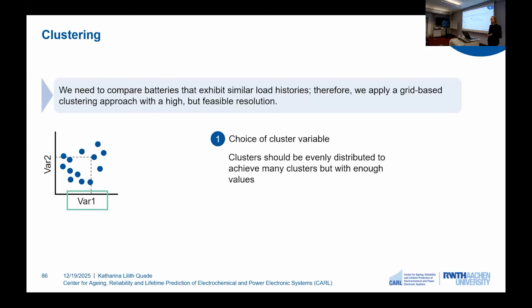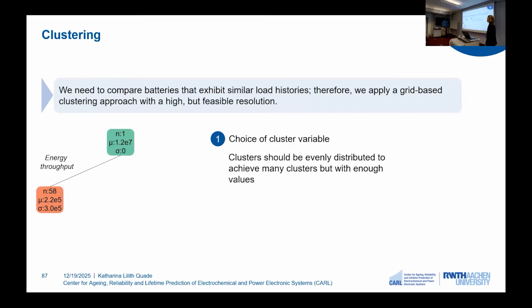The first step of our grid-based clustering approach is to determine the cluster variables. And here we do an iterative approach where we then analyze for each variable we cluster by how it affects the cluster sizes and also the spread between cluster sizes. And here you can see the workflow. We see for the green rectangle, we assume we only have 1 cluster and all of our data, so the 12 million data points, are inside of this cluster. And then we cluster by energy throughput for a fixed step size and also by mileage. And we can see that we have the same amount of clusters and we also have the same average values per cluster. However, the spread for mileage is higher than for energy throughput. And we want evenly distributed clusters, and that's why we stick with energy throughput.